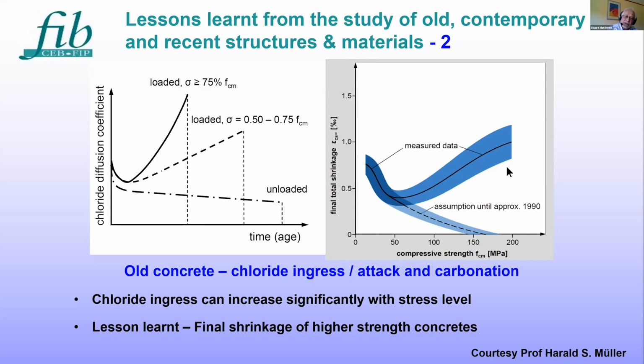And if we turn attention to the right-hand graphic, which shows total shrinkage versus compressive strength, you'll see that there's a downward branch to this, which was our assumptions on the behavior of high-strength materials until about 1990. But experience of measuring test data and performance of actual structures suggests that that behavior is not correct and much higher shrinkages occur for these high strength materials that we're now dealing with.